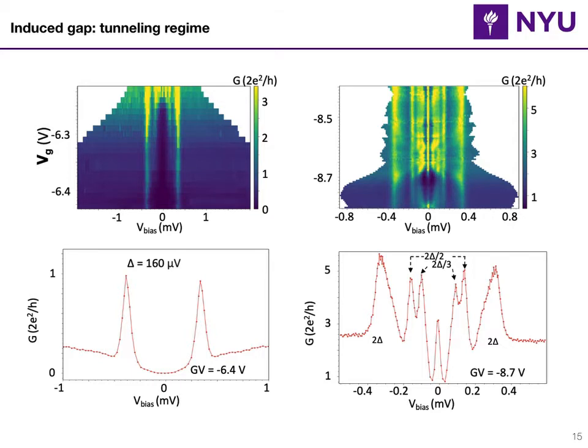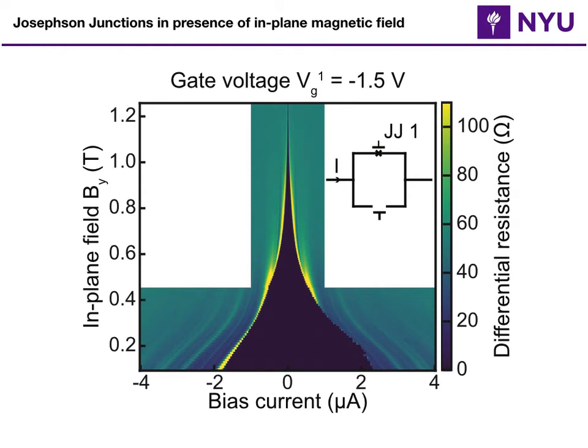Once we follow the recipe that we have been told by the theorists, we apply a magnetic field along the y direction, which is along the junction, and look at the critical field in the x direction here. Dark blue or black, I guess, on your screen is supercurrent, and you see that the supercurrent just diminishes up to 1.2 Tesla very monotonically. This data is taken at a gate voltage signified up there as minus 1.5 volts, where the Rashba parameter is very small, as I showed you earlier. This is in the density regime where there is not much Rashba spin-orbit coupling.